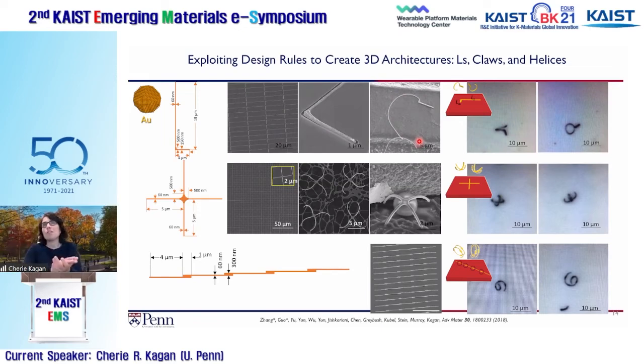Now, of course, when we put them on a substrate to image them, everything sticks to the substrate. But if you were to look at them in a solvent in an optical microscope and just watched as they tumbled in the solvent, you could really see that they have a three-dimensional shape that starts to form. And then we played on that idea. If we made plus signs and the arms bent, we get things that look like claws. We could make this sort of zigzag structure and they would start to form helices. So we really started to understand what kinds of structures we could create by using this approach.